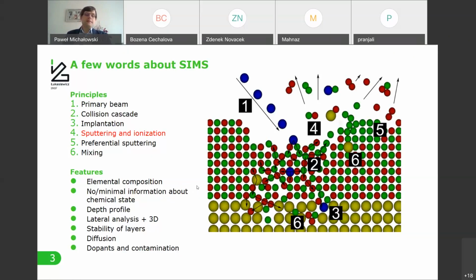The most common application is to create depth profiles. So basically, when we start to sputter surface layers, we start to drill a crater in the sample. So we not only can check the elemental composition of a sample, but we can also see how this elemental composition changes as a function of depth, going through all the layers in the material. Many tools, including mine, also have position-sensitive detectors, and thus lateral analysis can be done on the surface of the sample, and when combined with the depth profiling mode, fully three-dimensional images can be obtained.